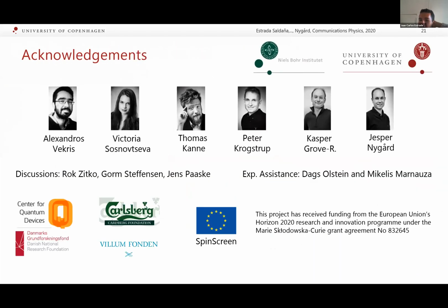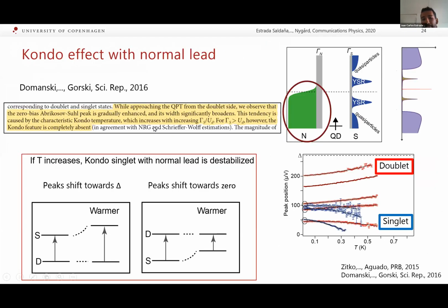And we actually have some idea that, well, in this paper by Domanski and Gorski, it was said that the Kondo temperature should be enhanced on the doublet side. So before the ground state transition, and this might lead to this change of direction in the doublet side. So with temperature, you know that the Kondo singlet will be destabilized. This is schematized here. As the system becomes warmer, the singlet will shift towards higher energy because the Kondo phase is becoming weaker in the normal lead. And when we are in the singlet ground state, then basically we will see our behavior. And maybe what we're seeing, the change of curvature, is because the Kondo effect in the total system, the normal quantum dot superconductor system, is different than just considering the quantum dot normal system separately.